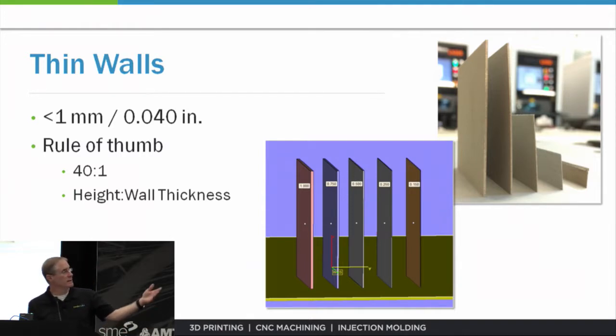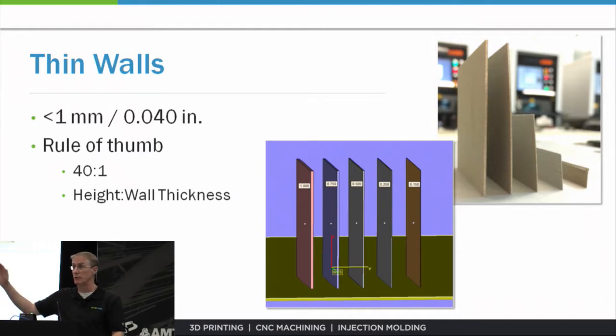So if you look on the far right in the picture of the actual part as it printed, what you can see is the thinnest wall, which was 6/1000ths of an inch. It made it up about 1/4 of an inch before it started to warp, right? If it's too thin, as it gets taller, it's going to have stresses, and those stresses are going to cause it to move. Well, the second that it moves and warps, the layers above it have nothing to adhere to. From that point forward, you're going to have a wall that's stunted, and the laser will continue to draw away. It's just going to draw away bits that get swept away by that recoater blade. And so that's what happened on the far right. It was too thin, it warped, and those subsequent layers had nothing to adhere to. And so it failed, right?